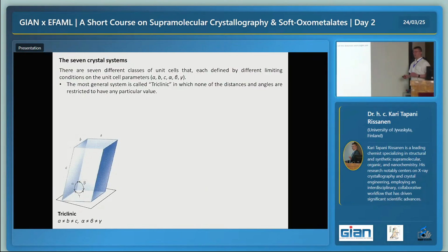So now, how many possibilities do we have to select the smallest possible unit? The point is that we have only 7 possibilities. Why is this? Soon you will see. We have to be able to repeat the same unit cell in all dimensions. If they were badly designed, with bad corners or bad axes, they would not fit. There would be empty space, which is impossible.